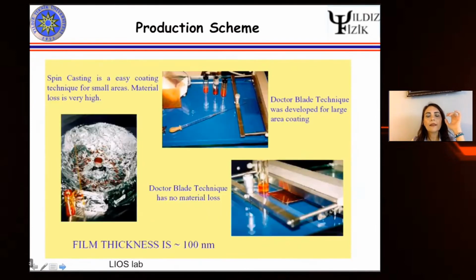If we look at the most popular techniques for the lab scale, we have two techniques: spin coating and Dr. blading. What is this? We have a substrate, and by programming the spin coater, we can let it run and it rotates. And depending on the concentration of your solution and the rotating speed, you can have thick or thin films. This is a nice method. It is quite a uniform film, but the problem is you lose a lot of material. As you can see, it spreads here, and this material is lost.